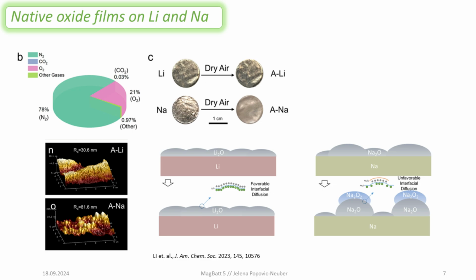And we can see from AFM images, also done, of course, in argon in a glove box, that the roughnesses of these surfaces will also differ. And if we go to the molecular level, we can try to imagine that these oxide surfaces are also different. So in the case of lithium, we have a dense layer of lithium oxide on top of lithium, while in the case of sodium, we can have both oxide and superoxide. And these might, from the starting point, also build more porous structures.